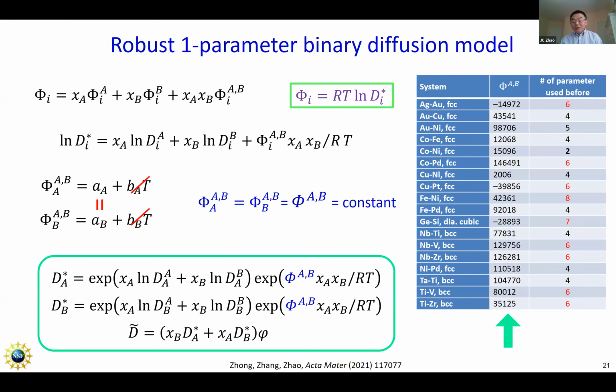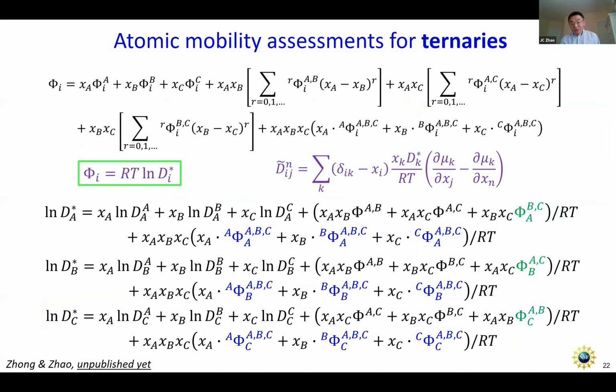So this is part of the beauty of the CALPHAD approach, right? You can describe the entire diffusion behavior of a binary system from a single parameter, a single constant. And that's how efficient it is once the model is established, that you can store the data and retrieve the data. That's how beautiful it is. I usually use the logarithm of D_i because that helps me understand the quantities. But if you multiply by RT, you get the regular mobility parameters. I think that's quite useful information.